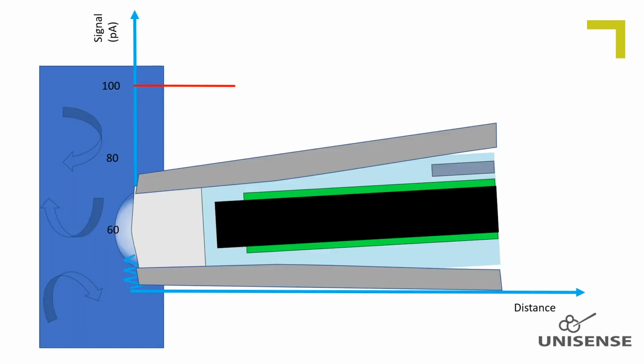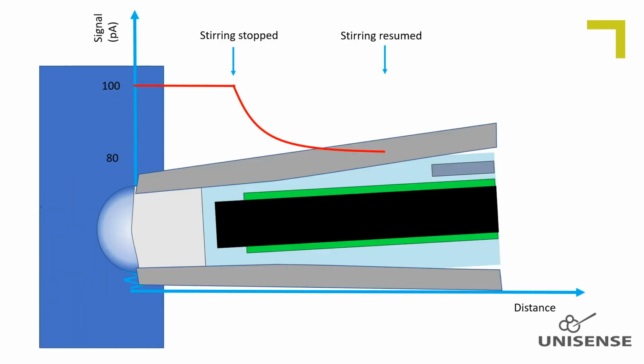The sensitivity to stirring is defined as the difference between the signal in stirred and stagnant sample with the same nitric oxide concentration. This is exemplified here where a sensor measures in a continuously mixed sample. When the stirring is stopped, the signal decreases more than 20%, which is typical for a standard range nitric oxide sensor. And when the stirring is reactivated, the signal is back to the original level. The large sensitivity to stirring will typically result in unstable measurements in nitric oxide containing samples.